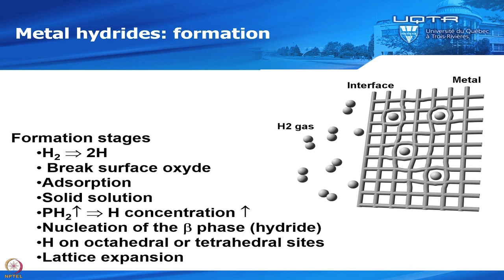So very quickly, just the steps for forming a metal hydride. First you have hydrogen in gas phase, and this hydrogen has to be split into two hydrogen atoms before entering, because in a metal hydride, what is stored is not an H2 molecule, but the hydrogen atom. Okay. So first you have to break this molecule. After that, the hydrogen has to break through. Usually you have a small oxide layer on the surface of your alloy, so it has to break through this oxide layer.